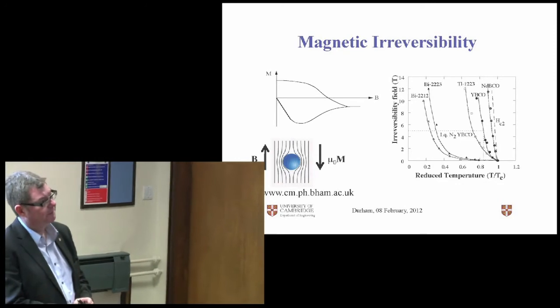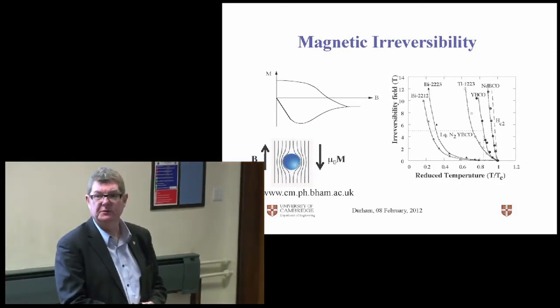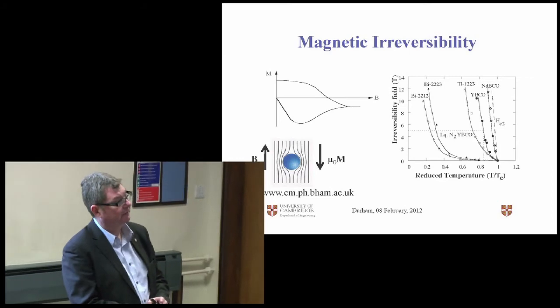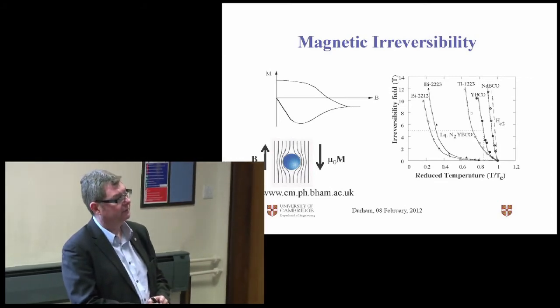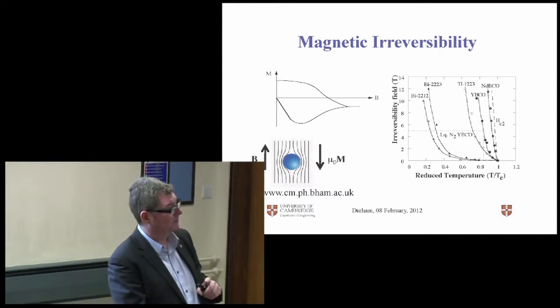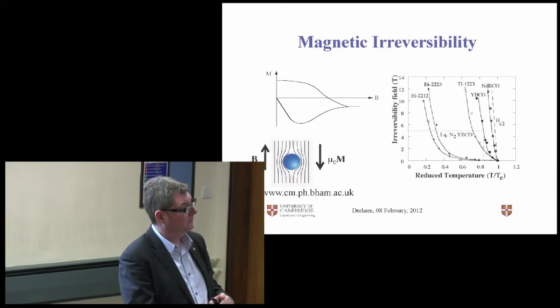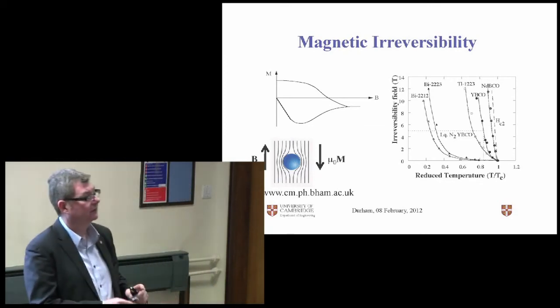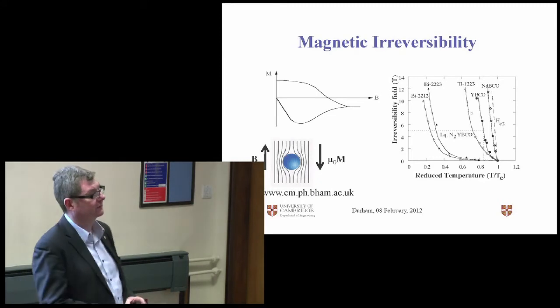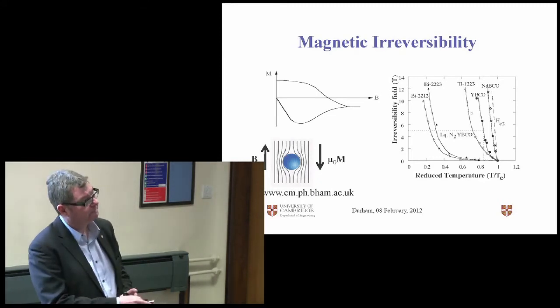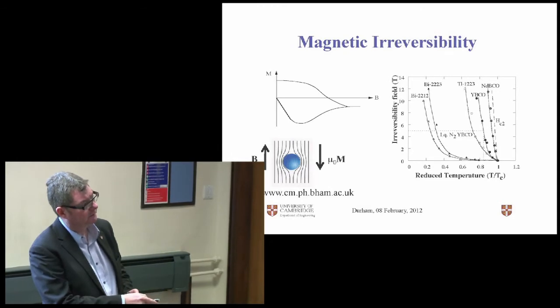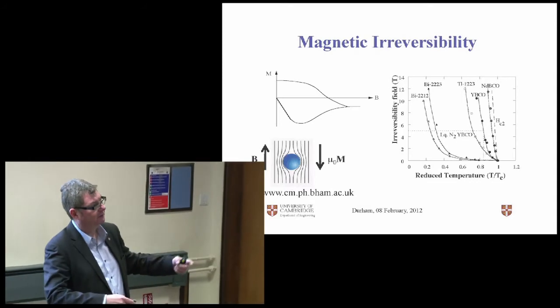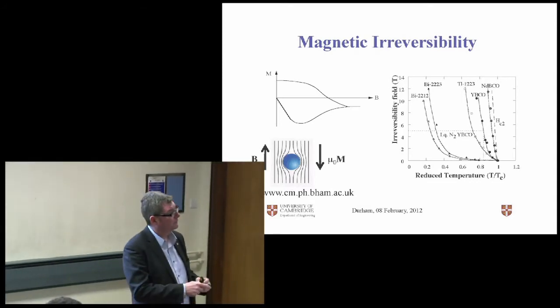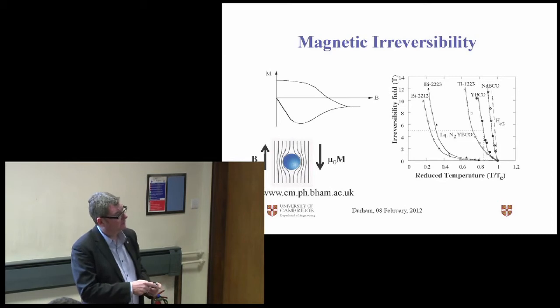Here's the applied field. Here's the equivalent of the field generated by the superconductor, or its magnetization. They're equal and opposite, so if we add them in the body of the superconductor, they cancel to zero. And since flux lines have no beginning and no end, that means they must be expelled from the superconductor. So this is an example of a Meissner state where the flux is being excluded from the superconductor because currents are flowing on the surface. If we then continue increasing the field, you can see the magnetic pressure here is greater than the magnetic pressure here. Eventually, flux is forced into the superconductor, and that occurs at some well-defined field here.